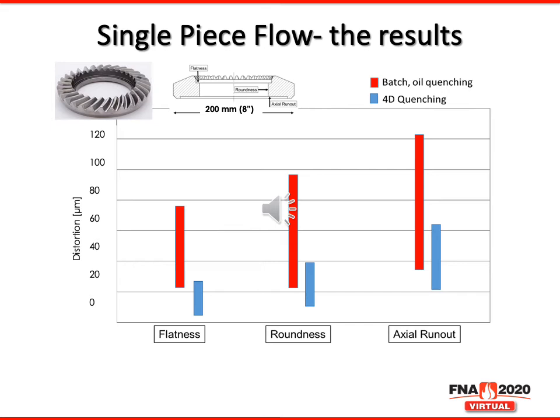Now, to be fair, the distortion doesn't disappear, but say in this case of the bevel gear that we've been watching develop through this sequence, the reduction in distortion for variables like the flatness, roundness, or the axial runout, when compared with traditional batch oil quenching, is reduced by up to 2 to 4 times, which is a remarkable decrease in distortion and may just be enough to remove most of the post-heat treating hard machining required to finish the manufacturing process of this part.